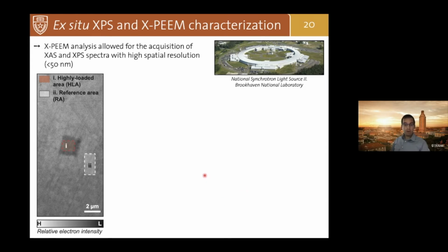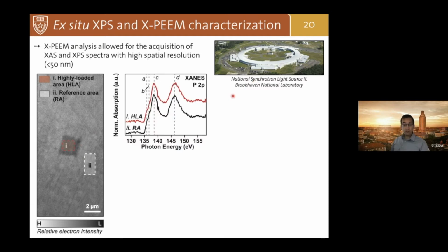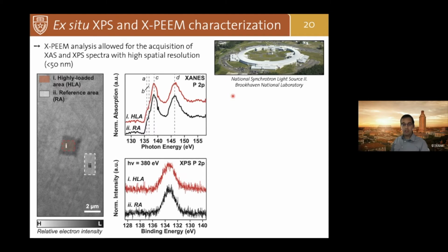So for addressing this problem, we have to use a national facility, the National Synchrotron Light Source. It's basically taking a sample which is 1 square centimeter and finding a spot which is on the order of 10 to the minus 8 square centimeters. So my student very patiently traveled thousands of miles and was able to see a 2 by 2 micron region over a 1 square centimeter sample in a very effective way in a few days at the synchrotron. I'm going quite quickly in this slide for one reason, and I will clarify that in a moment.